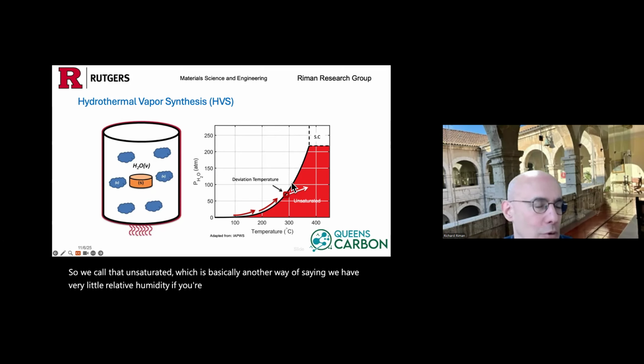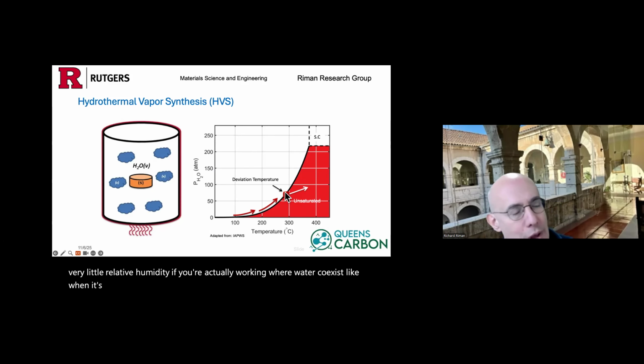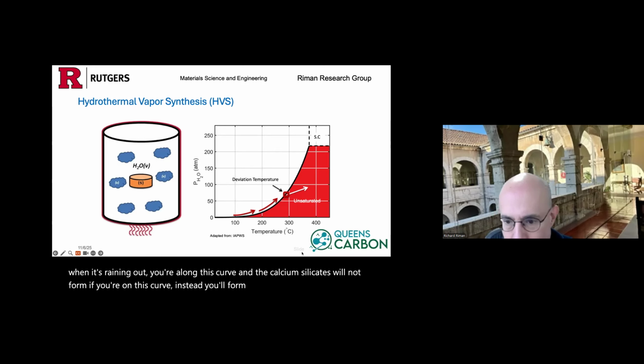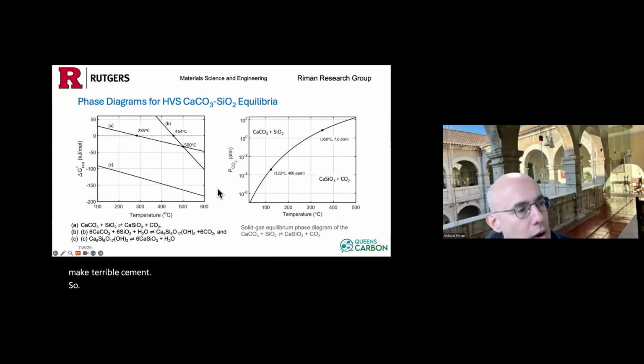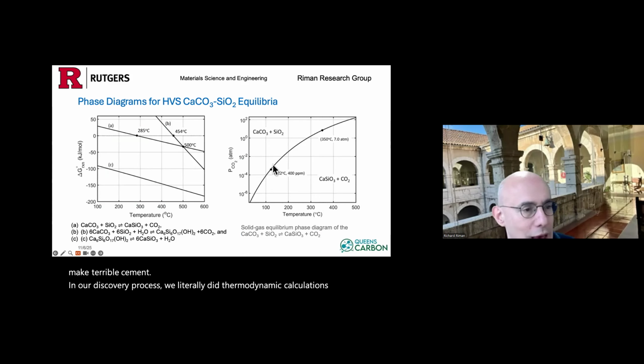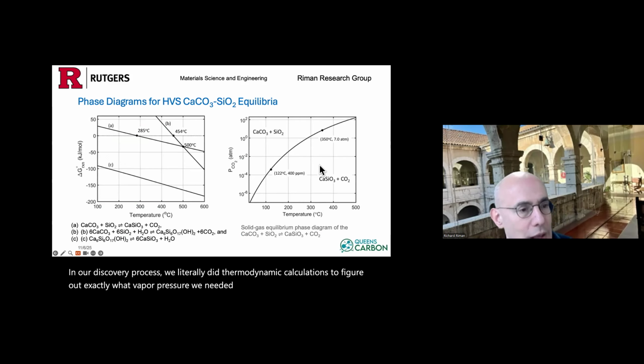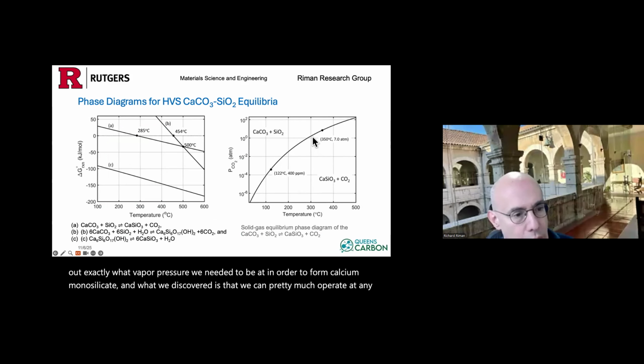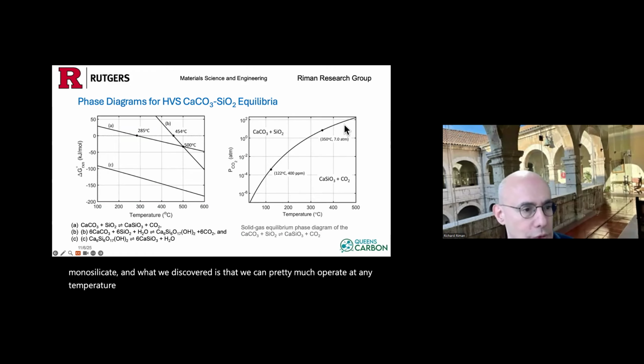If you're actually working where water coexists, like when it's raining out, you're along this curve. And the calcium silicates will not form if you're on this curve. Instead, you'll form hydroxides. And hydroxides make terrible cement. So in our discovery process, we literally did thermodynamic calculations to figure out exactly what vapor pressure we needed to be at in order to form calcium monosilicate. And what we discovered is that we can pretty much operate at any temperature above 300 degrees C.